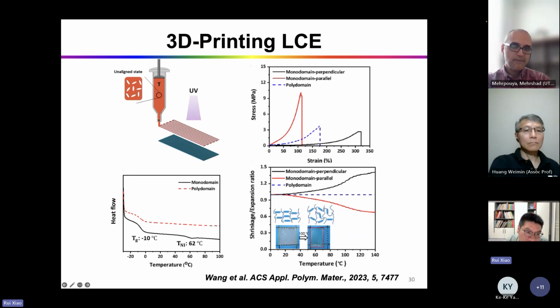The injection of the chemicals from the nozzle creates some shear force on the mesogens, so the mesogens align. Using UV light, you can fix this alignment, so you can create monodomain liquid crystal elastomers.